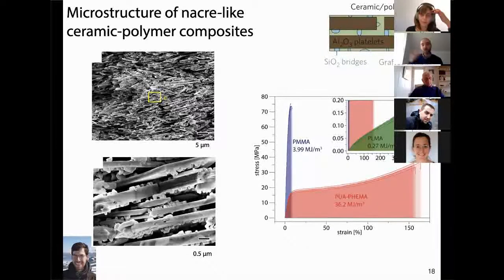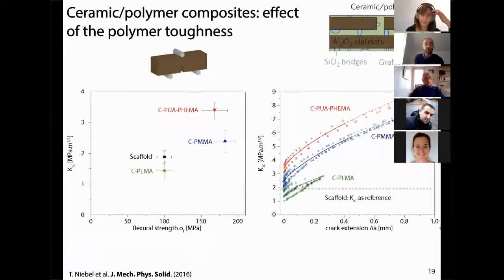So we can span 3 orders of magnitude in terms of toughness for the polymer. How does that translate in terms of toughness for the actual composites? So we've tested in fracture, in a single edge notch beam test. We've tested these composites. And what we end up with is, if we plot the flexural strength as a function of toughness, what we see is that more or less the tougher the polymer, the better.